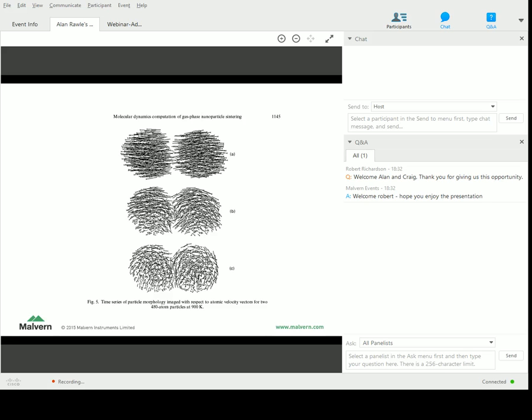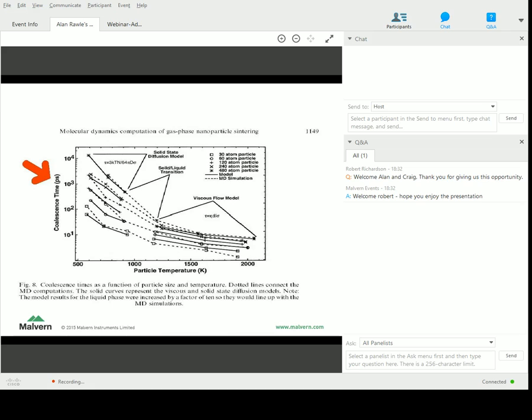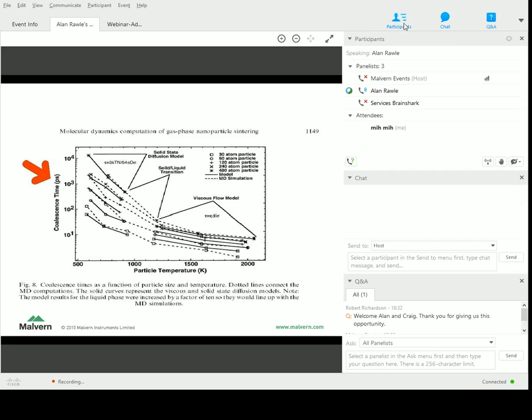And the NIST authors examined, or modeled, the diffusion of particles taking place. This is at 900 Kelvin. But the plot I'll show next, this one here, is the one that's, I think, crucial. If you look at the particle temperature along the horizontal axis, you've got a coalescence time for particles of various sizes, 30, 60, 120, 240, 480 atoms, which, you know, is significant size. If you multiply up 480 atoms by the size of the atom, you'll see that coalescence time is in picoseconds. So if you back extrapolate to room temperature, you're still causing particles to coalesce if they're small in a very small amount of time. And I think, again, this for me is a very enlightening plot.